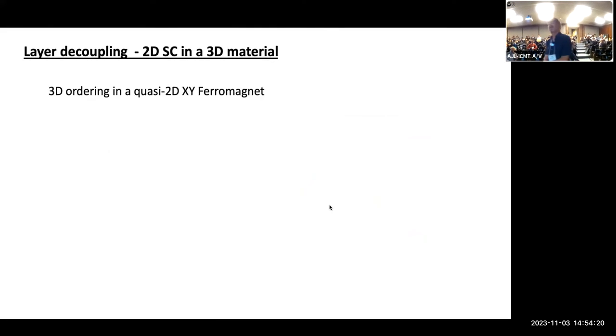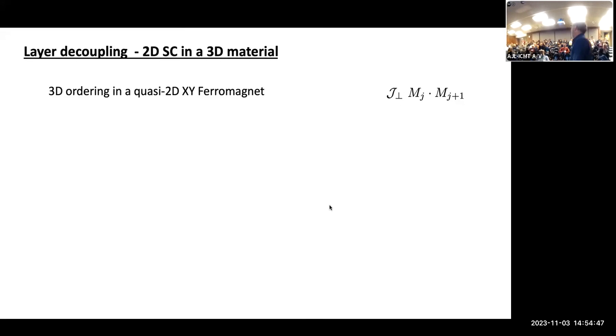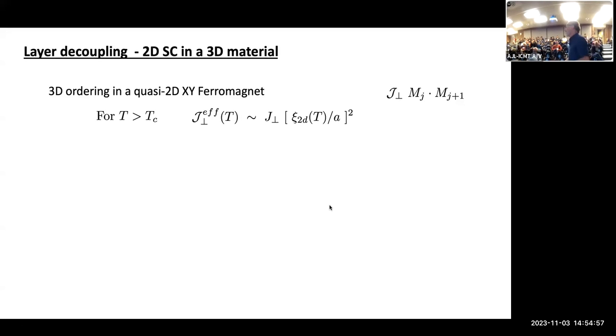Now, why is that so surprising? Well, let me remind you that as we develop order in 2 dimensions, we expect systems to become more isotropic, not less isotropic. And so let's imagine that we have, say, some planar 2-dimensional XY ferromagnet. That's my model of a superconductor. And then we have some interplane coupling between the magnetization in plane J and J+1. And then what you would at first say is that as long as J perpendicular is small compared to the temperature, maybe I could ignore it. But that's not the case.